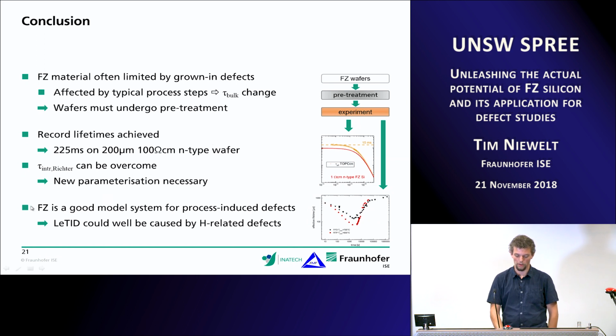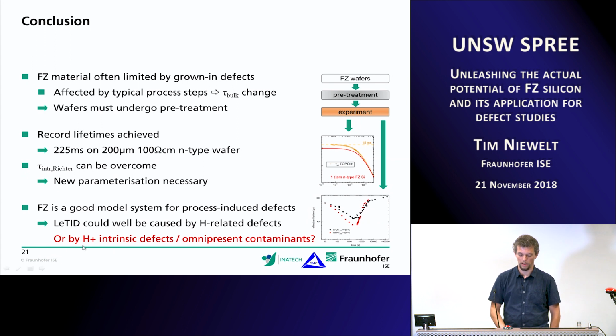And then I was showing you that float zone is a good reference material for everything that's introduced during the process, because there aren't too many defects around, so we don't have to rule out all the metals and so on, for example. So the defect could be caused by hydrogen, maybe in combination with intrinsic defects, or by something that every one of us or every group introduces to their wafers, but quite likely it's not completely caused by something that's already in the wafers to start with, because float zone is quite pure.